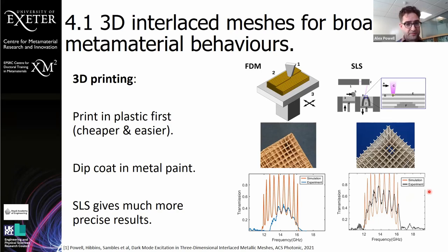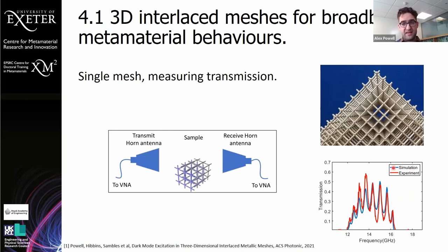So that's good. The experiment we're doing to get these results is we've simulated it in COMSOL, and we have a horn antenna on either side, shining radiation through the sample. We put the sample near the receive horn antenna so it's big enough to cover the whole area, and you don't get any waves traveling around the surface that affect the results.